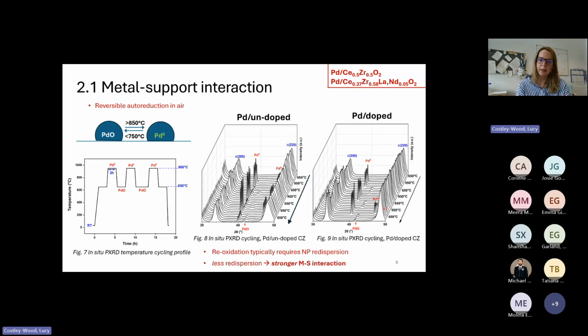Well, the reoxidation of palladium metal present as large metallic nanoparticles to the oxide requires the redispersion of nanoparticles, and that's quite well known in the literature. You oxidize the surface of the nanoparticle, the small oxidic part migrates away over the surface, exposing more metal to oxidize. So if this redispersion is less able to happen on the undoped material, it implies that the nanoparticles are more anchored, and that tells us we have a stronger metal support interaction.